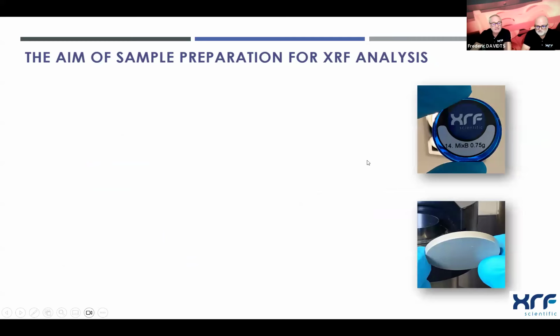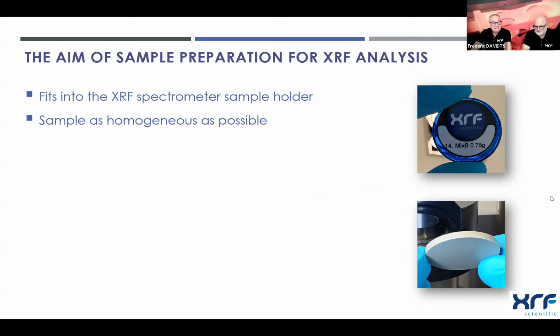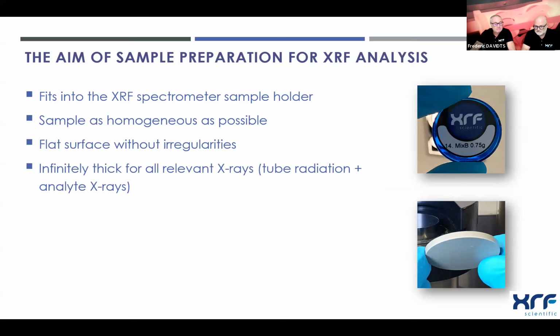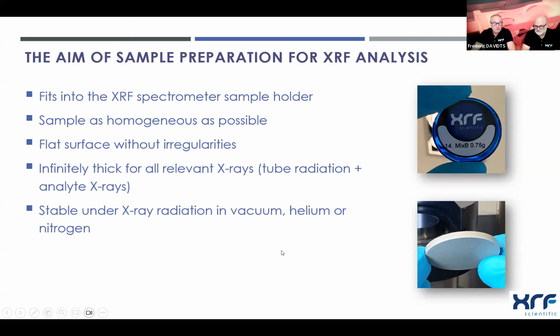Now, what is more specifically the aim of the sample preparation for XRF analysis? First of all, the sample must fit into our spectrometer sample holder. The sample must be as homogeneous as possible. It must have ideally a very flat surface without any irregularities, because these can lead to bad results. It should also be ideally infinitely thick relevant to the X-rays that penetrate the sample. And of course, it must be stable under X-ray radiation in vacuum, helium, or whatever other gas you may use. So we don't want the sample, of course, to drop into our spectrometer. That's bad.